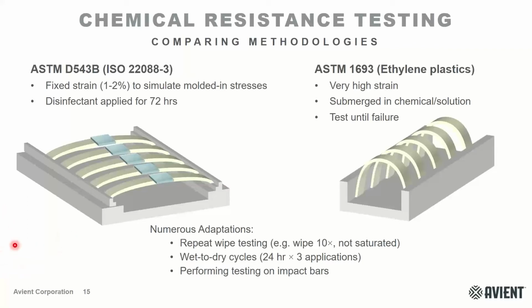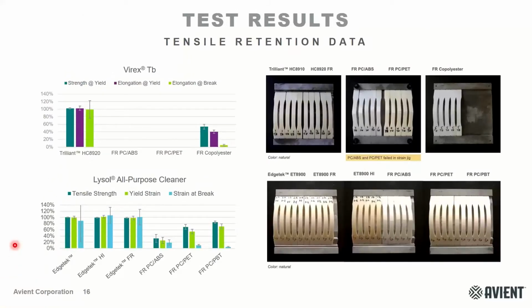So we do the ASTM D543, and I want to show you some of the results that we've had with our new materials, the Trilliant and Edgetek ET8900 series. In the image on the left, what you're looking at is a bar graph of tensile retention data. So when you do this test, typically you'll have a strain control that's put in the strain jig at the same strain level, and it's not treated with a disinfectant.